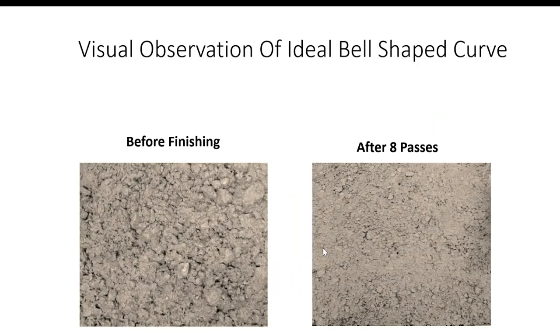And we say, well, what was wrong with this? Well, in this bell-shaped curve, this is what that float test looked like before finishing. And after 8 passes, it looked like this. After 20 passes, it still looked horrible. It just didn't finish well. And that was a big game changer for us.